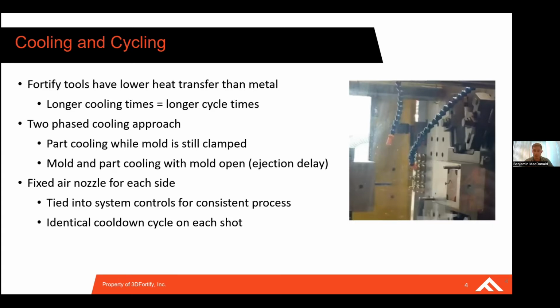So today we're doing this with just a fixed air nozzle that we have mounted on the mold press, and we're blowing compressed air on the surface of the tool. So our cooling process is really a two-stage process where we do just the initial cooling with the tool clamped. This is anywhere from 50 to 100 seconds with the tool clamped in order to solidify our part. We're just looking to get our part out of that molten phase into a solid phase so that we're able to do the bulk of our cooling with this compressed air.